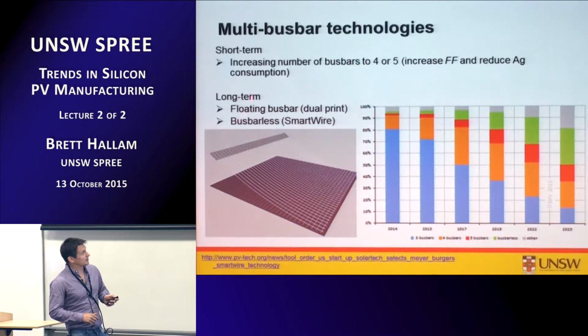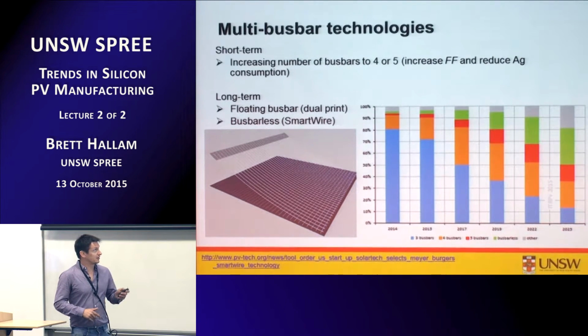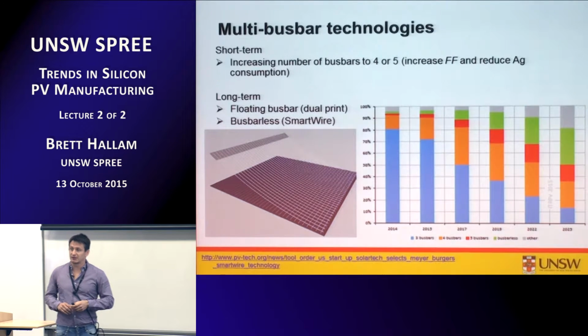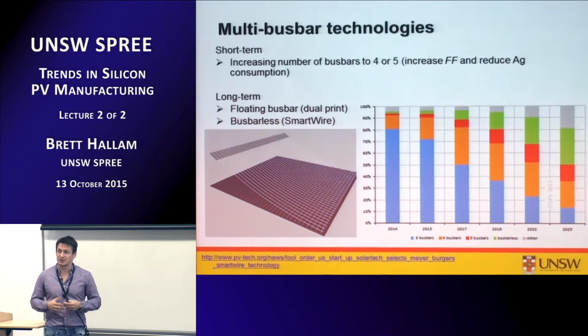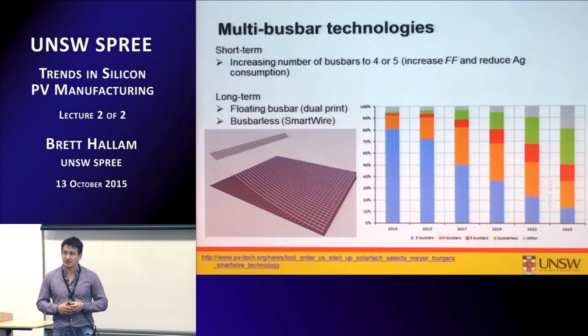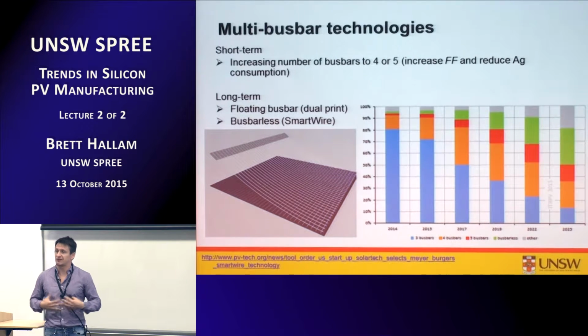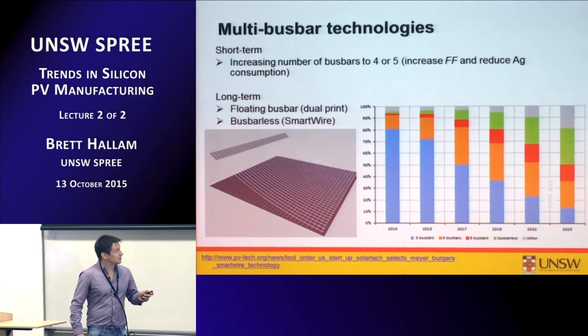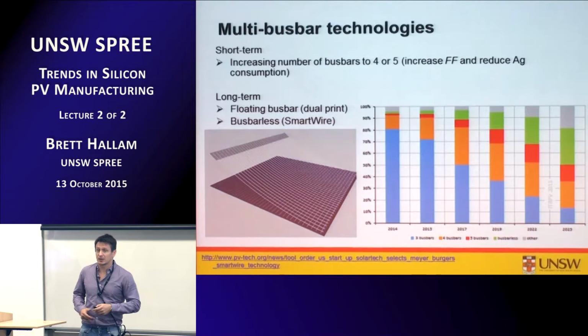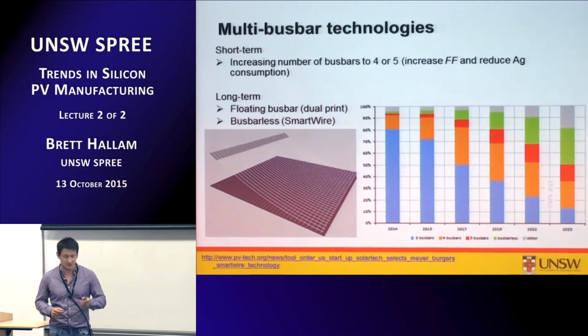In the longer term, there are also a couple of other technologies like floating bus bars, which I mentioned with dual print, a way to at least reduce some of the metal-silicon interface area. That's going to become more important as we go to higher efficiency solar cell structures. We only want a metal-silicon interface where we need it, otherwise it's going to hurt the J0 of the device and reduce the voltage. The other is going to a completely bus-barless design, where we only, say, screen print fingers onto the solar cell, and then use an interconnection process to effectively make bus bars on the surface.